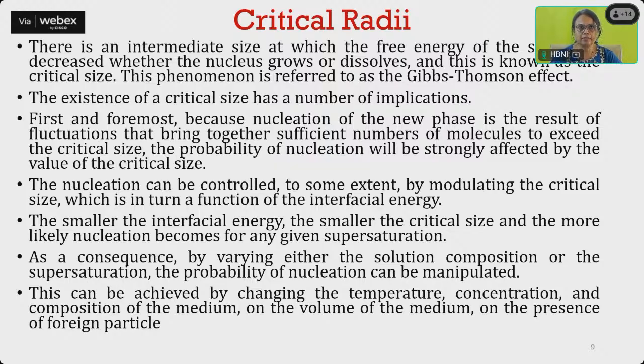The existence of a critical size has a number of implications. First and foremost, because nucleation of the new phase is the result of fluctuations that bring together a sufficient number of molecules to exceed the critical size, the probability of nucleation will be strongly affected by the value of the critical size. The nucleation can be controlled to some extent by modulating the critical size, which in turn is a function of the interfacial energy. The smaller the interfacial energy, the smaller the critical size, and the more likely nucleation becomes for any given supersaturation.